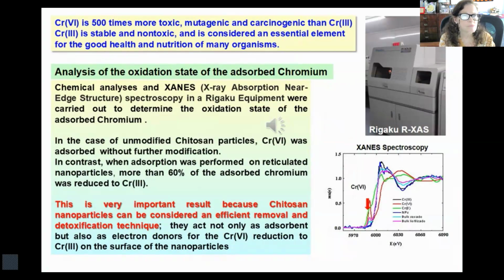Hexavalent chromium is 500 times more toxic, mutagenic, and carcinogenic than trivalent chromium, which is stable and non-toxic. The oxidation state of the adsorbed chromium was determined by chemical analysis and by X-ray absorption near-edge structure spectroscopy in a Rigaku equipment. In the case of unmodified chitosan particles, hexavalent chromium was adsorbed without further modification. In contrast, when adsorption was performed on reticulated nanoparticles, more than 60% of the adsorbed chromium was reduced to trivalent